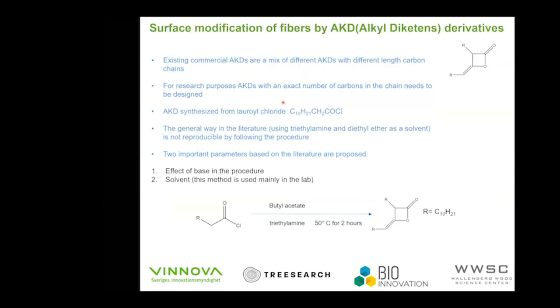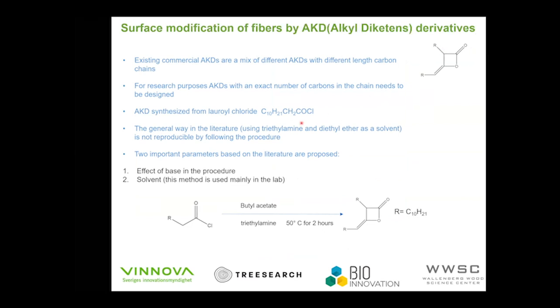The second method for better mixing between the TMP fibers and the polymer is surface modification of fibers by AKD, or alkyl ketene dimers, which is used a lot in the industry, and this is the structure here. But the problem is that the existing commercial AKDs are a mix of different AKDs with different carbon chain lengths. For my research, I need an AKD where I know exactly how many carbons are in the chain. So we have synthesized different AKDs, for example from lauroyl chloride, or we synthesized stearoyl chloride from stearic acid, and then made an AKD from that.